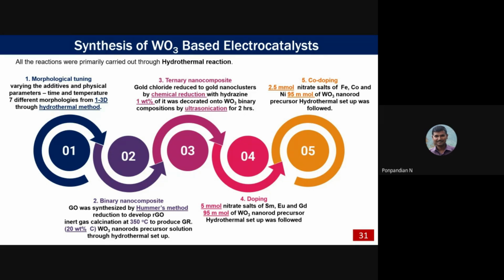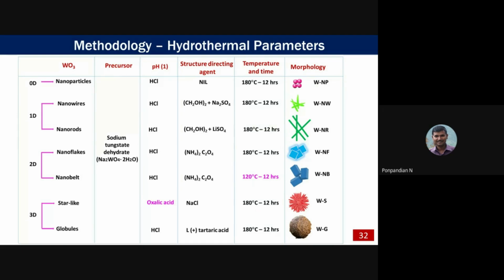Here you can see, this is what I explained, how one can make this morphology. The second objective is a binary nanocomposite, that is tungsten oxide with carbon, that is graphene. Again the ternary nanocomposite, where the tungsten oxide is together with graphene and gold, and again the rare earth doping, and co-doping with the transition metals. These are the materials which we have prepared for our application. You can see the morphology. These are the different preparation techniques for preparing the different morphologies of the tungsten oxide. You can see all the basic elements, the precursor materials.